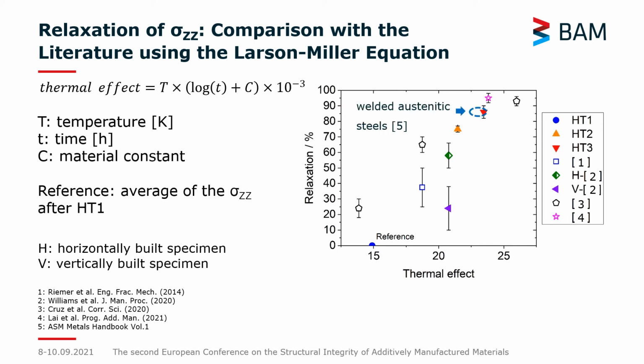And this actually corresponds well with what is suggested for welded austenitic steels. So basically, when applying heat treatments between 840 and 900 degrees for 1 hour, we have a stress reduction of 85%, which in this case applies to the heat treatment at 900 degrees for 1 hour that was applied to the laser powder bed fused 316L. Moreover, what we can see from this plot is that since we are almost at the plateau already, thinking back about the heat treatment at 450 degrees for 4 hours, we can assume that this first heat treatment did not affect the residual stresses heavily.